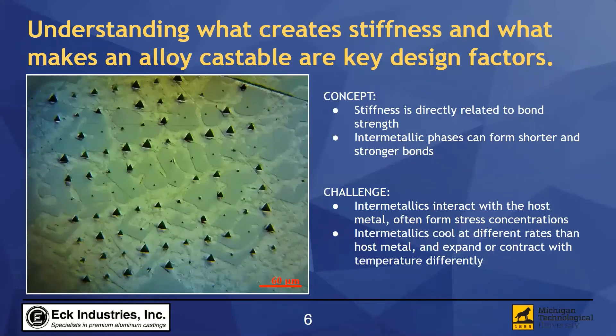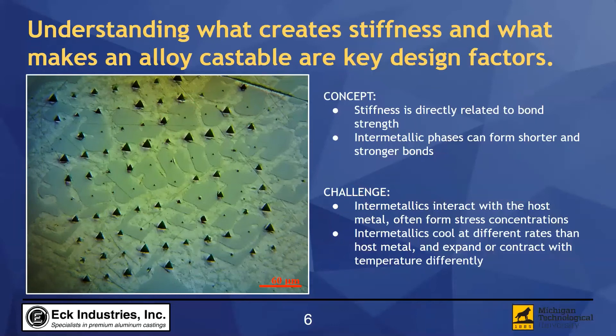Now I've mentioned the stiffness increase we're looking for and this idea of remaining castable, but let's look more into where stiffness really comes from and how that sets up for castability. On the left, you can see a micro scale image of aluminum alloyed with just nickel, and you can see areas that are darker and look smooth with lighter areas around them. These darker areas are called intermetallics, and they form in the casting process. These intermetallics are what help to make an alloy stiffer because they form shorter and stronger bonds that take more input energy to break. Now knowing that, it might be logical to think to try and form as many intermetallic phases as possible, but there is a challenge to casting. Intermetallics cool, expand, and shrink at different rates than the material around them, so they can often form stress concentrations that lead to cracking in casting. Our design needs to find a balance between the stiffness gained from intermetallics and the complications to castings that come with them.